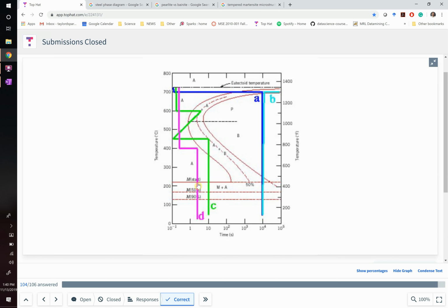If you were to heat this thing back up above the eutectoid and let it sit long enough, it will become pure austenite. And then if you quenched it down to the blue, the second green line right here at 450, then you'd end up with 50% bainite. But because we didn't do that, we basically took it from one furnace at 600 degrees. We put it in a different furnace at 450. The stuff that had already transformed from austenite to coarse pearlite, it's still there. We can't undo that unless you go back and you heat it up again.